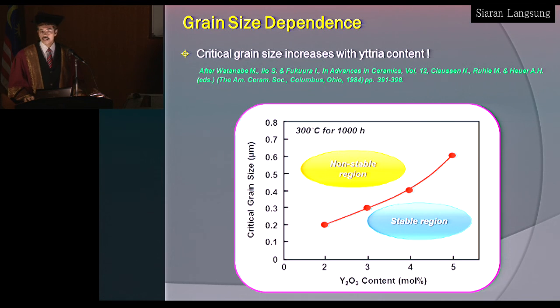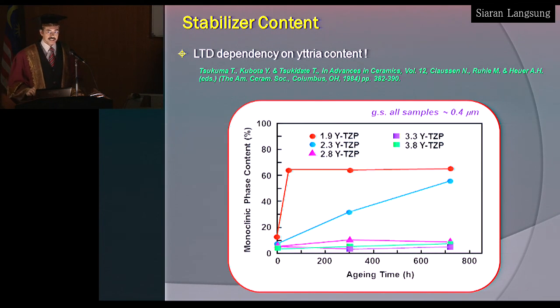There is a critical grain size postulated that controls the phase transformation, and this critical grain size depends on the stabilizer content. That red line shows you the boundary. For example, if we take 3 mole%, the critical grain size limit is 0.3 microns. If the grain size exceeds this limit, it goes into an unstabilized region, and upon exposure to a steam environment, it transforms. In terms of stabilizer content, that is the yttria added to stabilize the high temperature tetragonal form at room temperature, it has an effect as well. Increasing the stabilizer content from 2 mole% to 3 or 4 mole% obviously suppresses or reduces the phase transformation, as the graph shows.